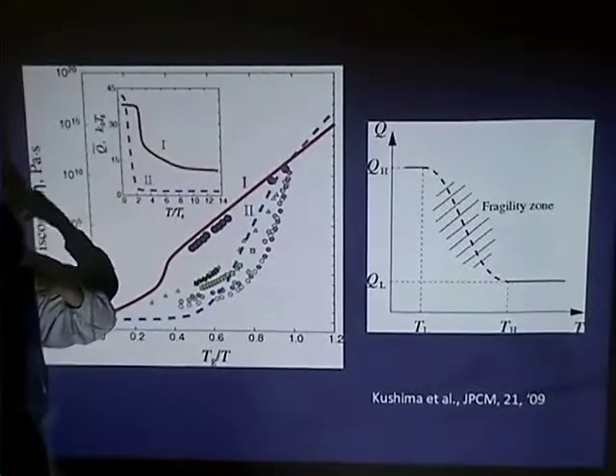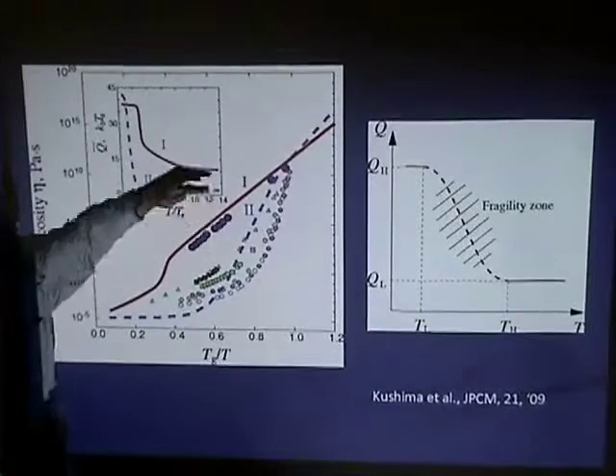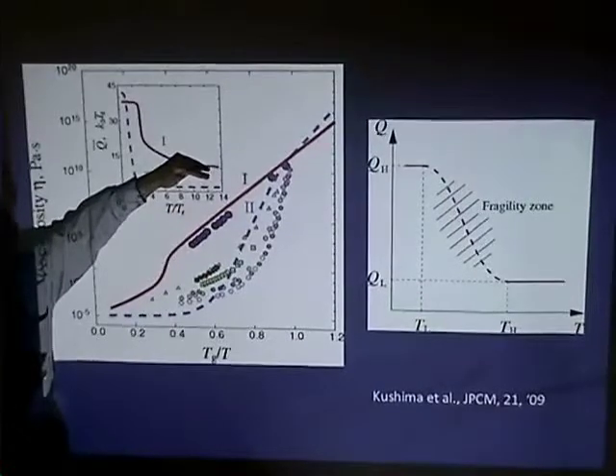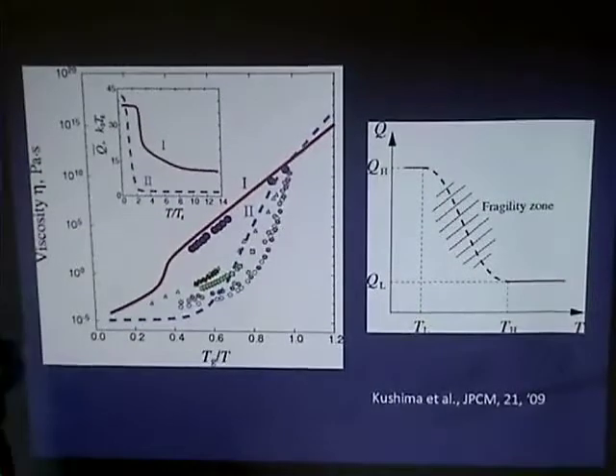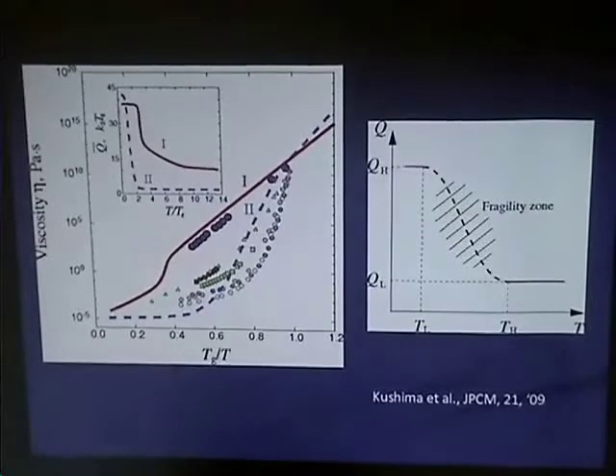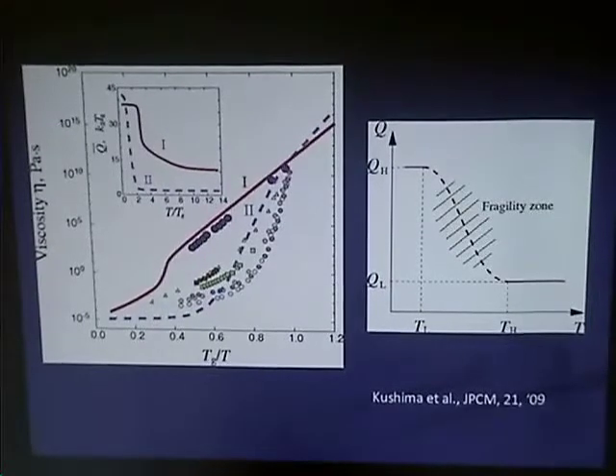All right, this just came out of the calculation, so we didn't insist. But basically, what it's saying is that at high temperature, the fragile liquids have a much lower activation energy compared to the strong liquids, simply because the bonding is different. Chemical bonds are just stronger in silica than in binary Lennard-Jones.